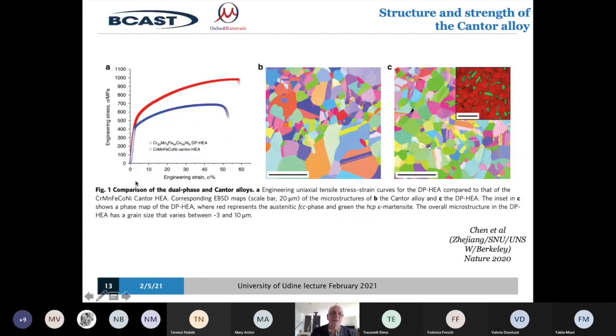This is the great properties they have. So this is what happens when you put a stress on a material. This is the level of stress, and this is the amount that the material strains, the amount that it stretches. Initially, it just stretches elastically, and then it begins to deform more with a permanent set, and that's when it curves over like this. This is the original Cantor alloy, and this is one of the modified Cantor alloys. Now, ceramics and rocks don't show this ability to deform, to change their shape. They just stretch, but they go up to quite high levels of stress, and then they just fracture.